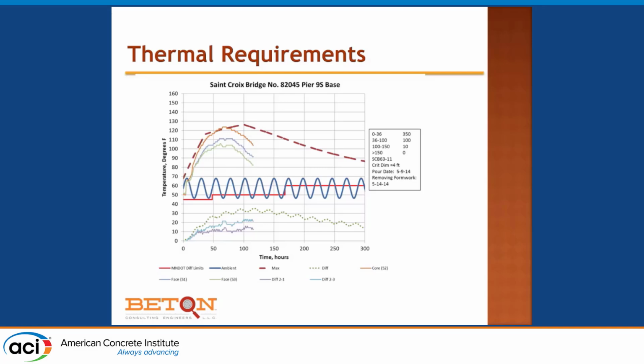Here's some data that shows you our predicted model for temperature, our actual model for temperature, and our models for differential. This mixture is in conformance. This one happens to be a pier base. This is not a cross beam, but it could easily have been. But you can see we have a temperature rise of only about 75 degrees in a member that is 4 feet in thickness. Our peak occurred faster than we anticipated or predicted, and it is dropping faster, and that's because we use the same type of approach that you would conceive for a load resistance factor design.